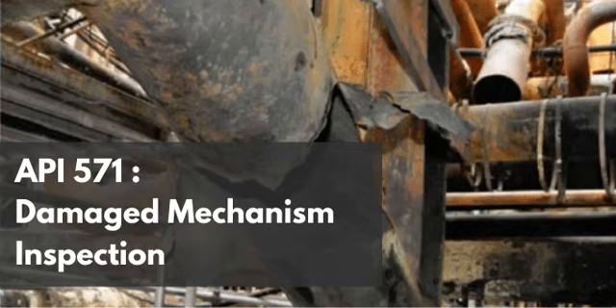I like that. Thanks. So if you take a heavy steel ball and drop it on the polycarbonate shield, the shield might dent, right? Right. It'll gouge or warp, maybe. Yeah, but it absorbs the kinetic energy through plastic deformation. It yields, and that is toughness. Exactly. But if you drop that same heavy steel ball onto a sheet of tempered glass, the glass doesn't dent at all. No, because it has incredibly high compressive strength. Right. But it has almost zero toughness. So instead of absorbing the energy and yielding, it just instantly shatters into 1,000 pieces. And what 885 degrees Fahrenheit embrittlement actually does is it slowly, over years of service, fundamentally change the crystalline structure of your flexible, energy-absorbing, polycarbonate-like steel into that rigid, unforgiving glass.